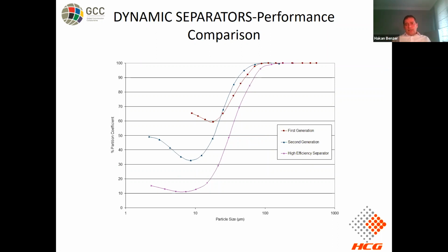Chronologically, the development of the dynamic separators started from the first generation to the second, and recently the high efficiency separators are in operation in many applications. As you can see here, the air used in the classifier is quite critical, and with the high efficiency separation system, we can reduce the bypass to below 10%, and we can achieve very steep, very efficient separation if the classifier is suitably designed according to your material.